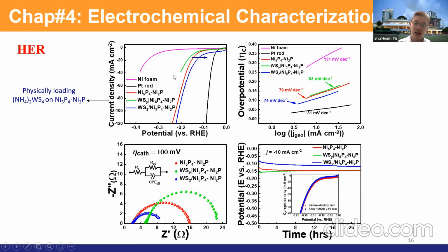It is better than the nickel phosphide, and is also better than nickel foam, and also the sample that is not being heat treated. So our hybrid sample is better than the other two control samples. We also find that the Tafel slope is lower compared to others. The lower the Tafel slope, the better for the catalyst reaction.